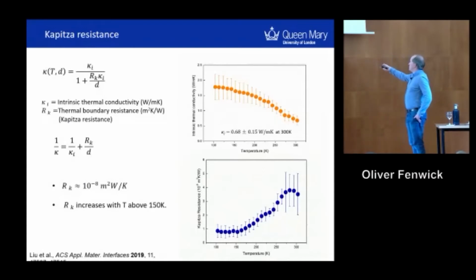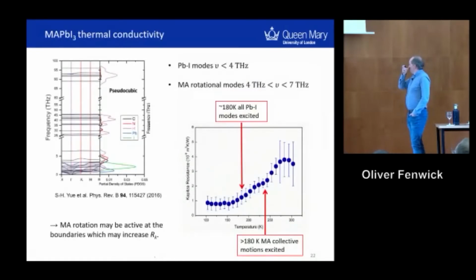We see a Kapitsa resistance that's in the right range for what is reported for most materials, so around about 10 to the minus 8 meters squared Kelvin per watt. What's a little strange is that it increases as you go up in temperature. It's quite low down here, at 150, 160 Kelvin, but has increased by a factor of 3 or 4 by the time you get to room temperature. We don't have a complete answer to that.